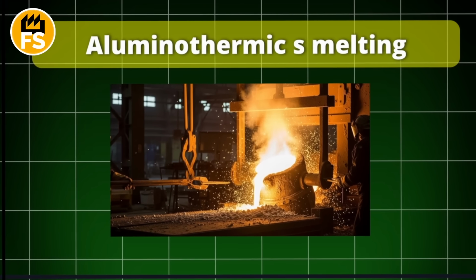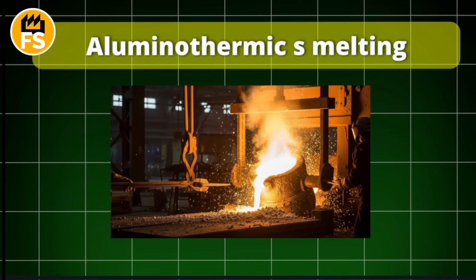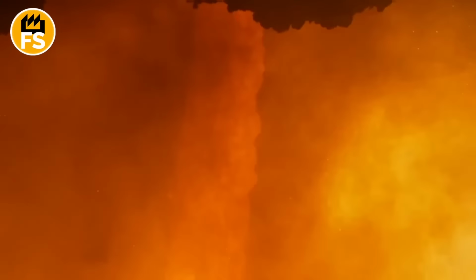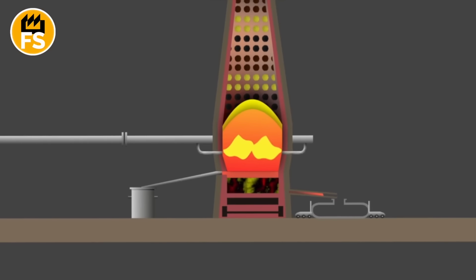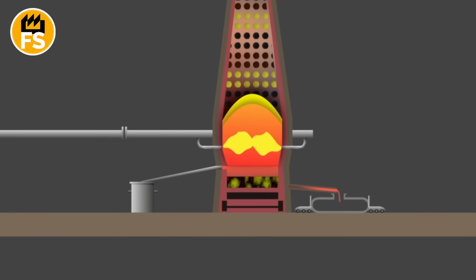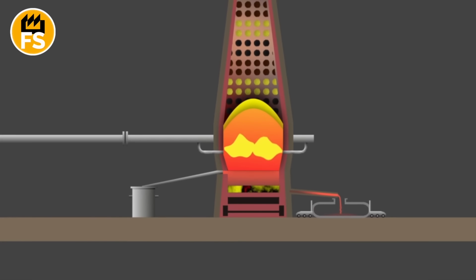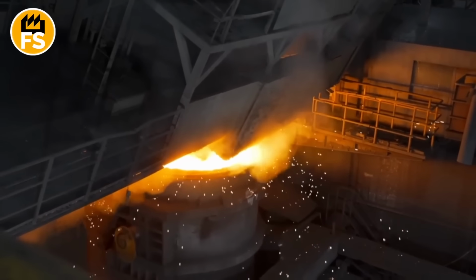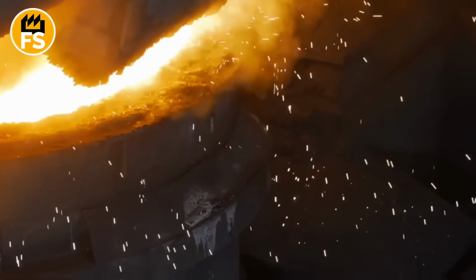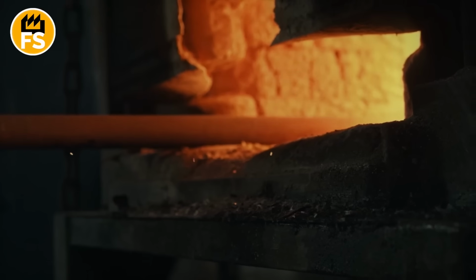Aluminothermic smelting, an older but effective method for small batches. In reaction crucibles, they mix molybdenum with aluminum powder and iron, then ignite it with a magnesium ribbon. The exothermic reaction instantly heats the mixture to the required temperature, reducing the metal in 5 or 10 minutes. Slag is removed mechanically. This method is cheaper but less pure.